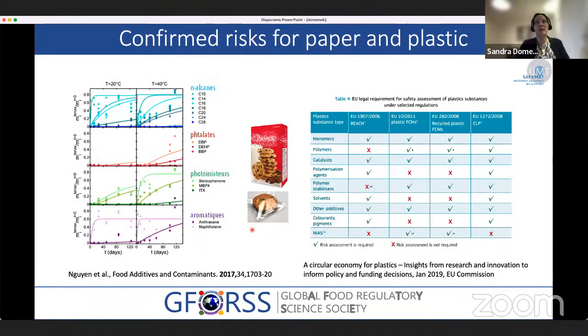There are confirmed risks for paper and for plastics. And here this slide is only to tell you about an experiment we were making. Just because you put your food inside of a virgin polyethylene pack, you are not on the safe side when you put it inside a recycled food container, as we were showing that this is not a functional barrier. You have almost no retarding of the migration of dangerous substances through the polyethylene inside the food. So in the European regulation, this NIAS problematic needs to be managed for the food contact materials and also for the recycled food contact materials.